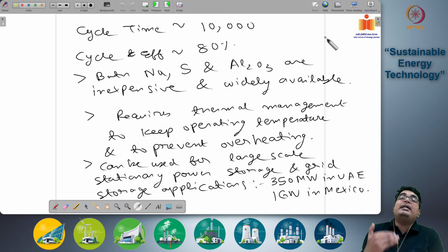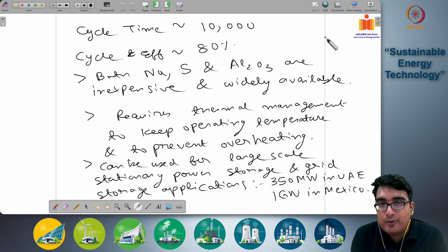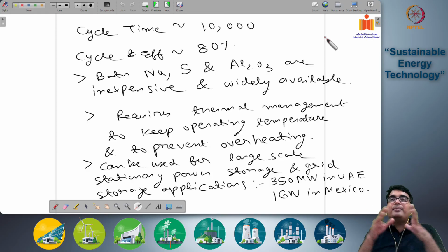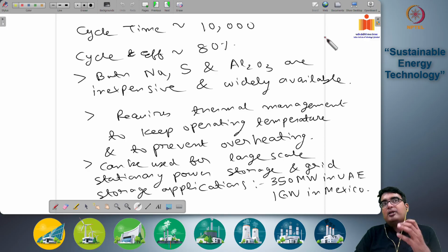And it has a very high cycle life of 10,000. So once a sodium sulfur battery is established, it can run for a very long period of time. Cycle efficiency is not that great, around 80%, because a lot of the energy is also wasted in heat. But the advantage is that sodium, sulfur and alumina are all inexpensive and widely available. Okay, so the material costs are significantly low.